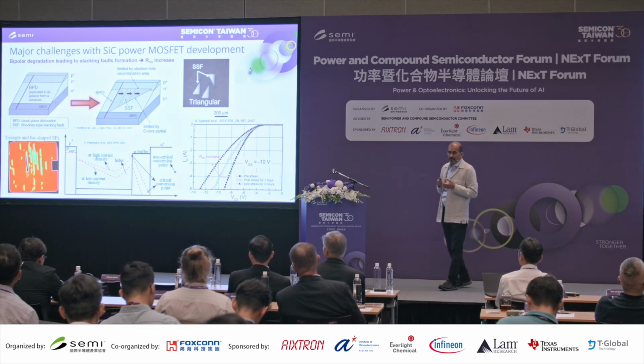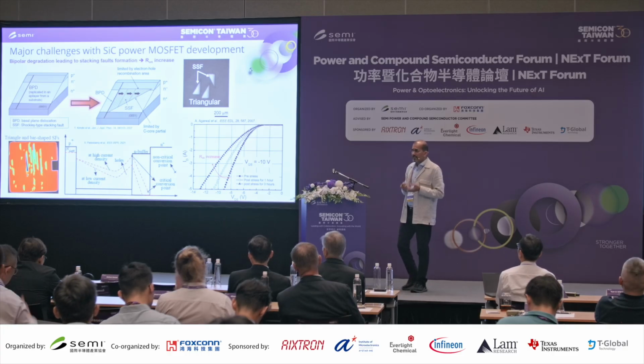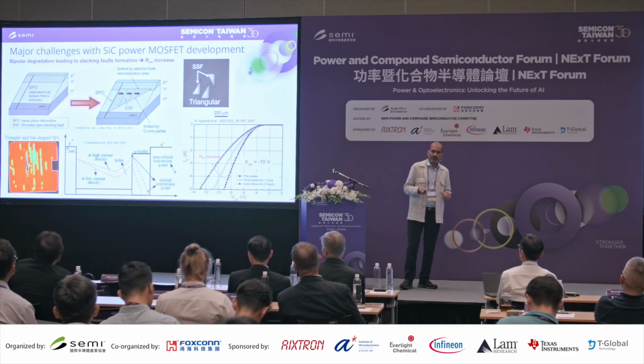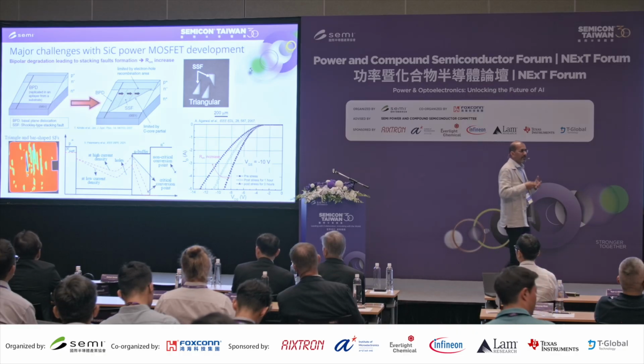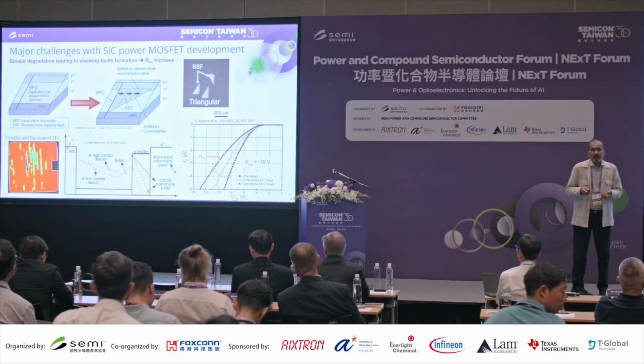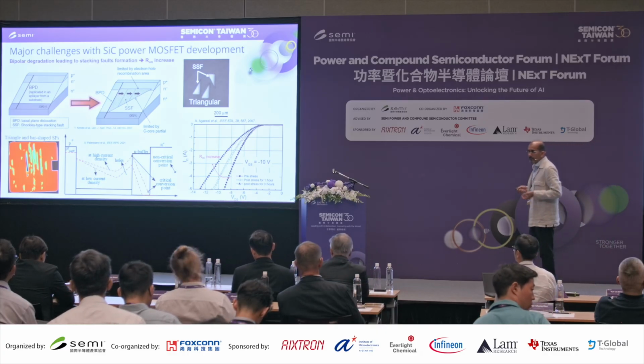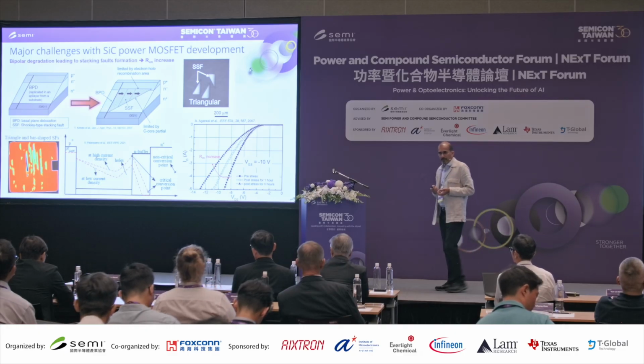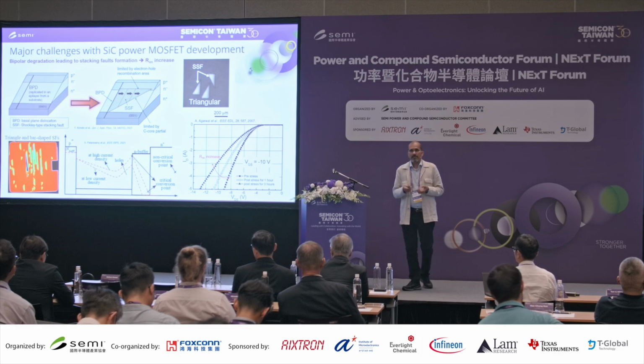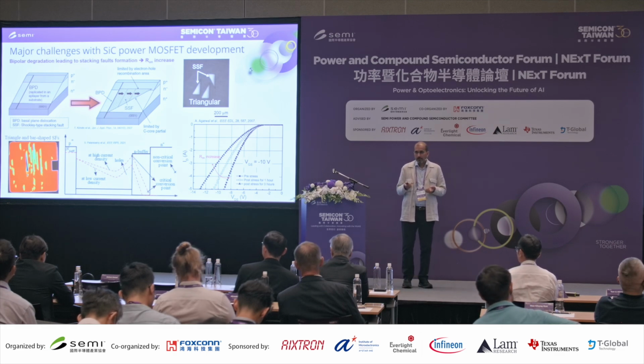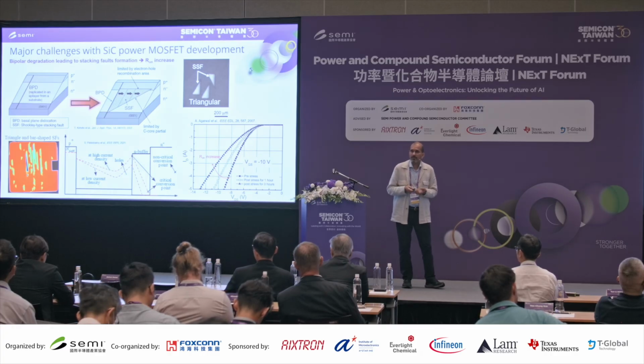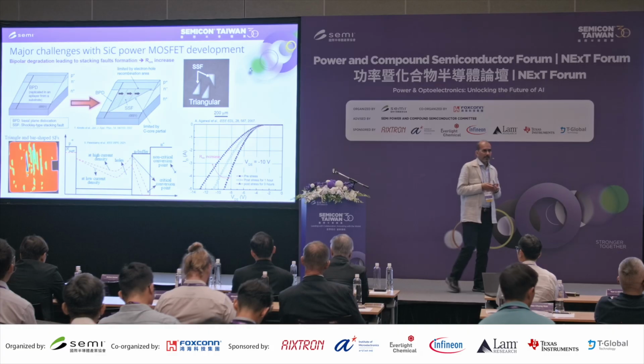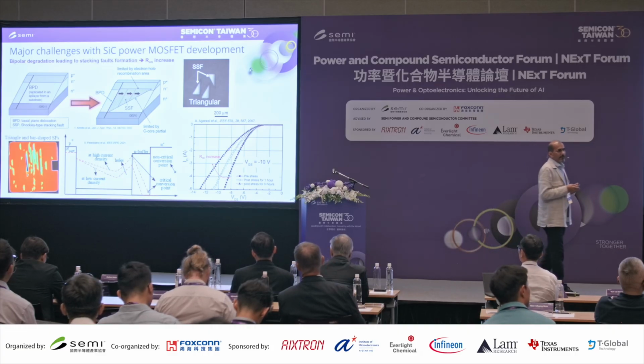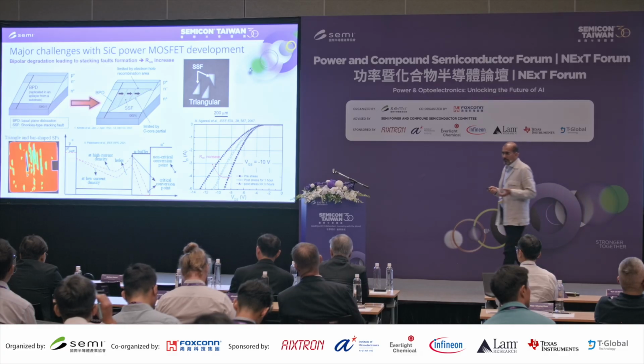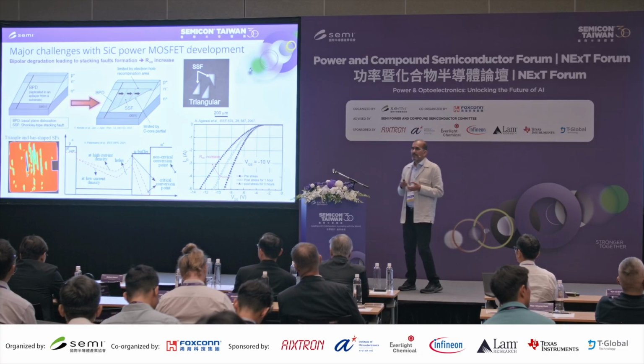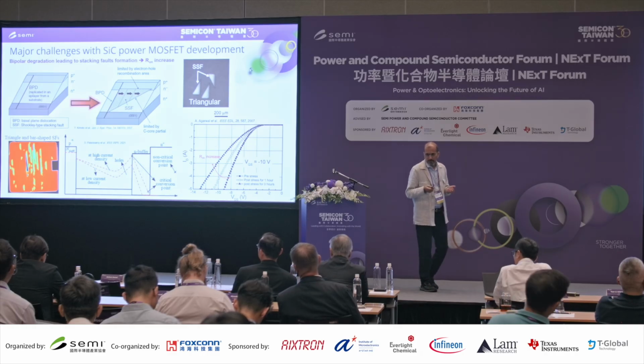Another problem in silicon carbide is the extended crystal defects in the substrate. They start from the substrate and propagate into the epitaxial layer. The epitaxial layer provides the device layer on a carrier substrate. If you don't have the know-how of the epitaxy, you end up with a poor epitaxy layer, the device layer, which has a lot of extended defects, particularly BPDs, basal plane dislocations, which are huge reliability concerns. Once you stress the body diode, they expand into Shockley stacking faults, and that results in an increase in the body diode resistance, an increase in your RON, and also creates problems in the leakage current.